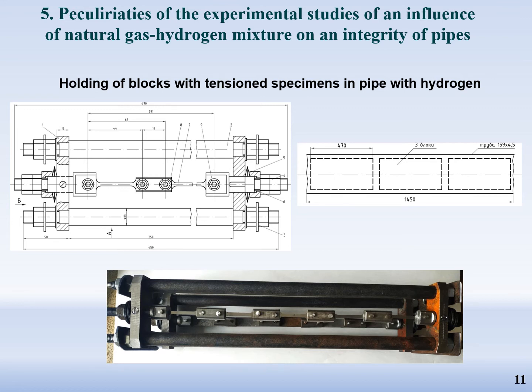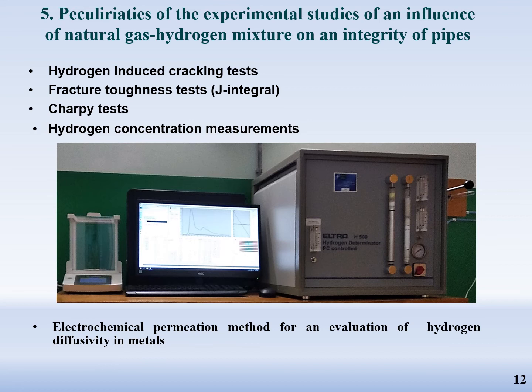We should also remember that hydrogen can leave a metal after taking specimens out of the pipe with gas-hydrogen mixture. So we plan to store specimens in liquid nitrogen before the next tests. Our program of tests predicts the most important studies, namely hydrogen-induced cracking tests, fracture toughness tests, the J-integral method, Charpy tests, hydrogen concentration measurements, electrochemical permeation methods for evaluation of hydrogen diffusivity in metals, and microfractography analysis for estimation of the influence of hydrogen on micromechanisms of steel fracture.